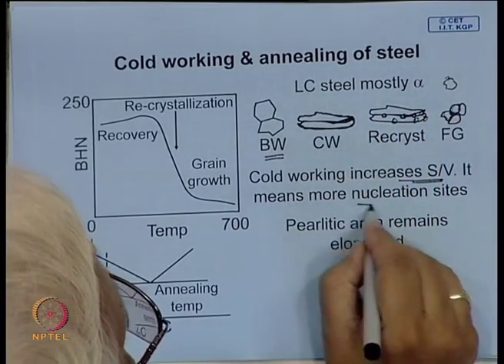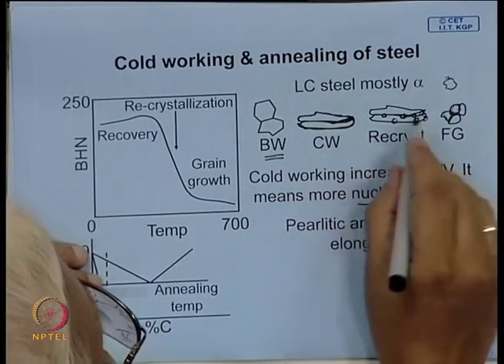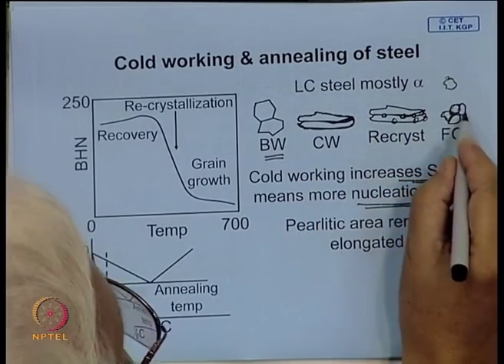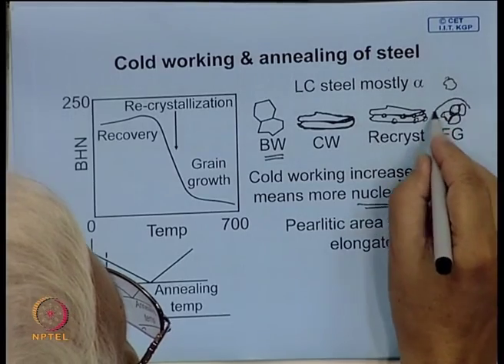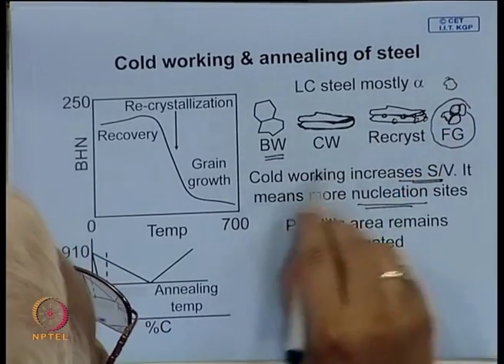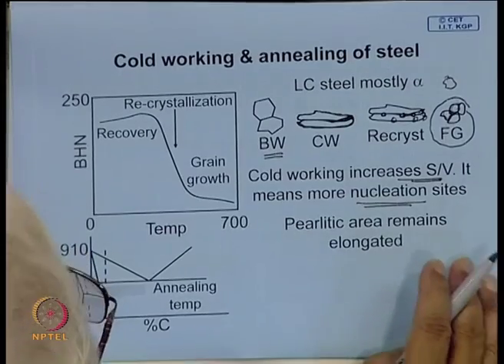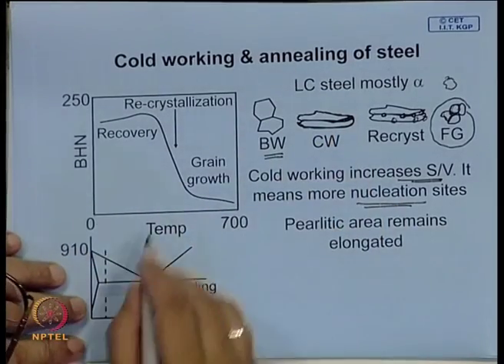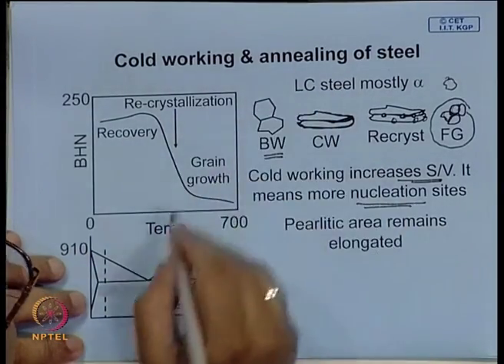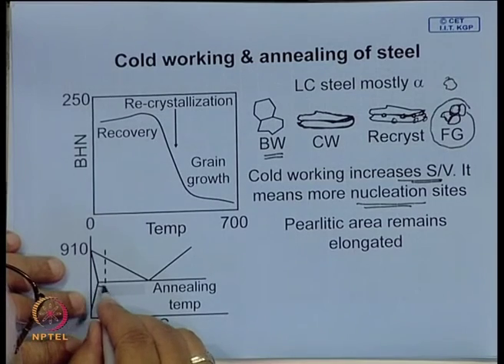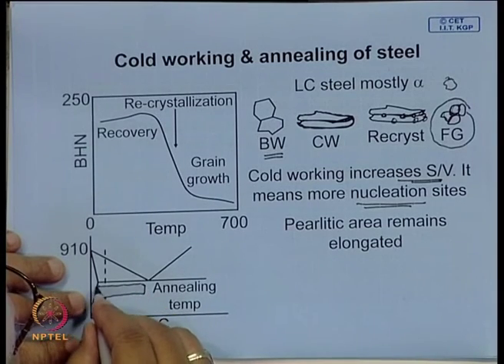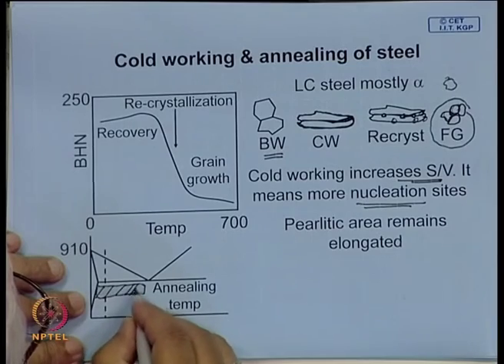So, it means it is more nucleation site, and higher the cold work, finer will be the grain. And by controlling the amount of cold work, it is possible to control the grain size, and usually the annealing temperature for cold working, after cold working of low carbon steel, is in this regime. You do not go to the austenitic region.